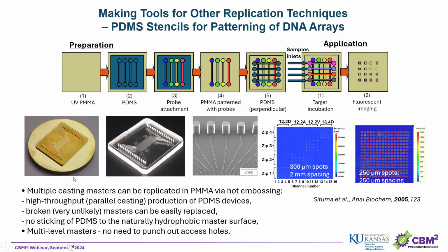And using this type of casting tool has a huge advantage over the regular route when it's done in the lab, where you lithography pattern SU8 resin on silicon wafers. One thing is that from the single brass tool, you can make multiple replicates in the PMMA, right? So we can set ourselves up with multiple casting tools, so our production process is much higher, it's much faster, right? We're not dealing with making multiple wafers via lithography of SU8 on silicon. We'll just do a couple more embossing steps and we have our tools, right?